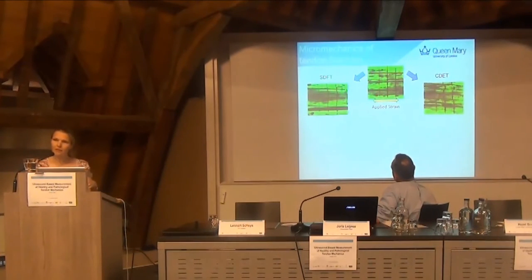So I showed you those different methods, so I'm going to talk about some on the confocal microscope to start with, ways of investigating mechanics within the tissue. This is a study we did where we took tendon fascicles from our energy store and positional equine tendon, stained all the collagen and then just bleached a grid on it. So you can stretch the tendon under the microscope and see how it deforms. Quick look at the pictures and I got quite excited. They look different before we started.